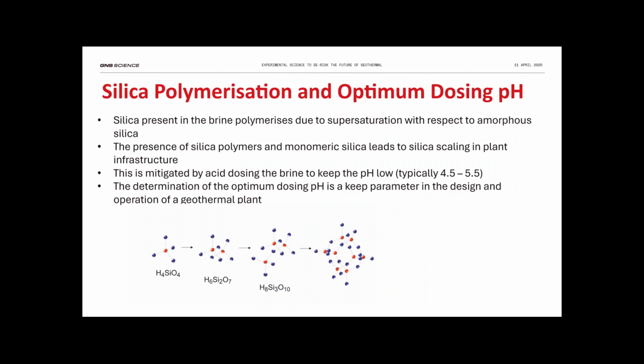Why is it important to get the optimum dosing pH? It's because if you're going too low, you're using excess sulfuric acid, which costs money, but also corrosion of the infrastructure is a serious problem. But if the pH is not low enough, then you have the potential of silica polymerization occurring in the plant or in the reinjection lines, which is an expensive problem to solve. So you want to get that sweet spot of the pH whereby the silica doesn't polymerize for a long enough period of time that it is able to get back down the well. So if you don't mitigate the problem, you end up with this, which is silica scale.